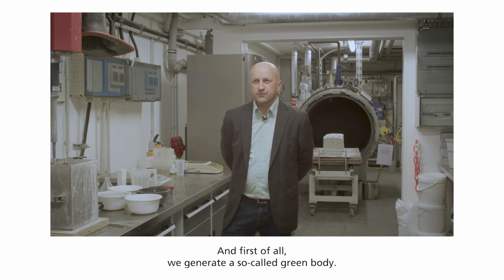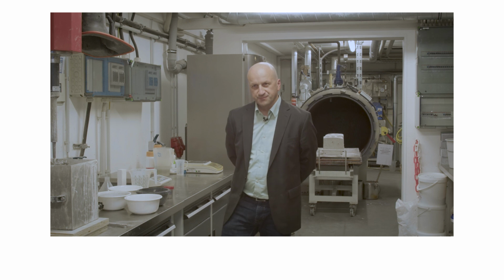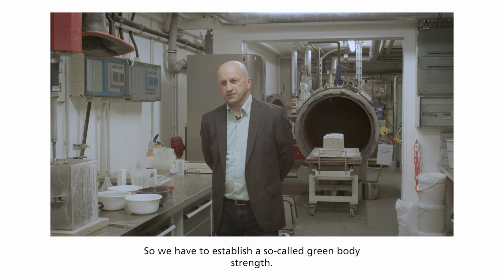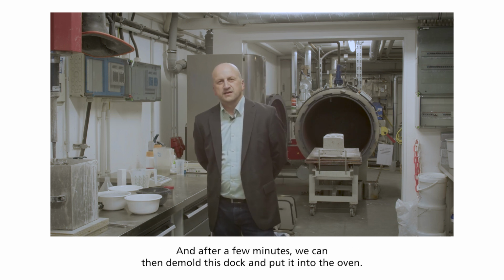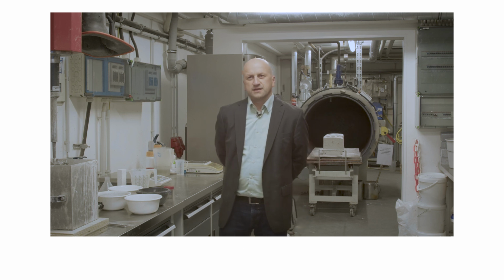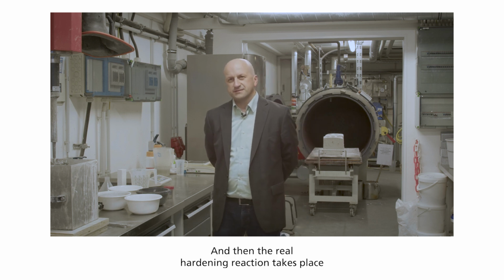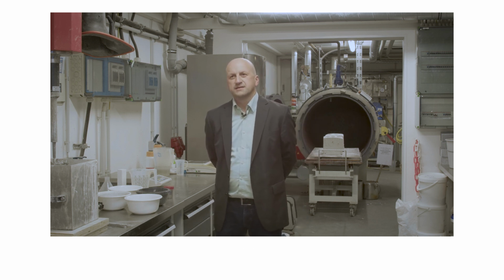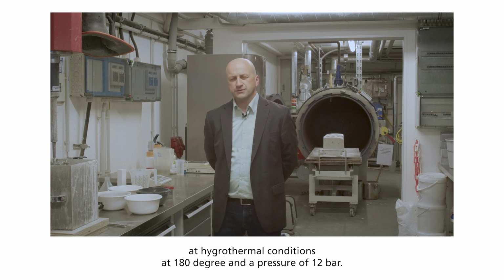And first of all, we generate a so-called green body. So we have to establish a so-called green body strength. And after a few minutes, we can then demold this and put it into the oven. And then the real hardening reaction takes place at hydrothermal conditions at 180 degrees and a pressure of 12 bar.